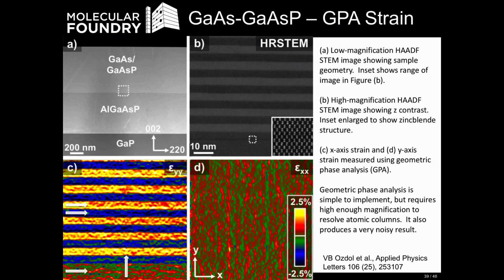This is strain perpendicular to the growth direction in C and parallel to the growth direction in D. And so overall, it shows what you'd expect. This film is epitaxially locked, so you don't get any strain in D. It's just a noise field, more or less. But in C, you can see the different lattice layers of these alternating strain-matched semiconductor materials. But once again, this study has a major limitation. There's quite a bit of noise introduced by the geometric phase analysis, and our overall field of view is only about 50 nanometers by 50 nanometers. So what we want to do with four-dimensional STEM experiments is get the same quality of data, but over a much, much larger area. And that's what I'm going to show next here.